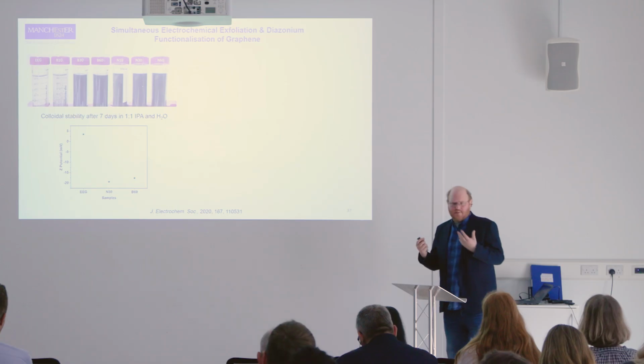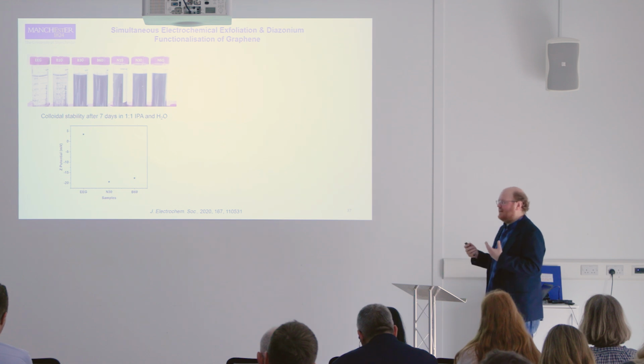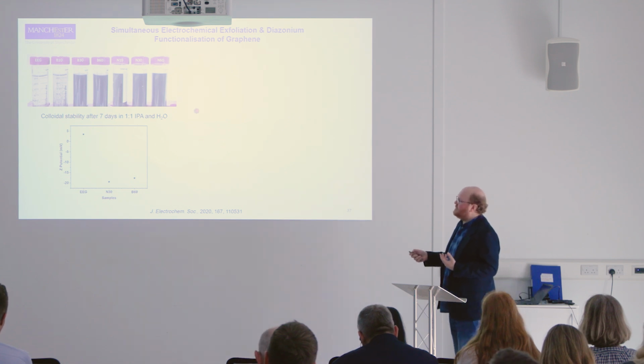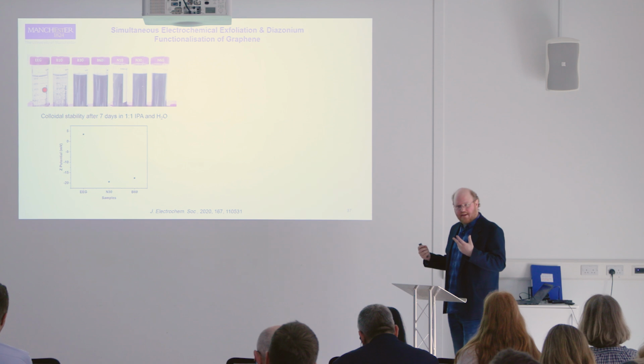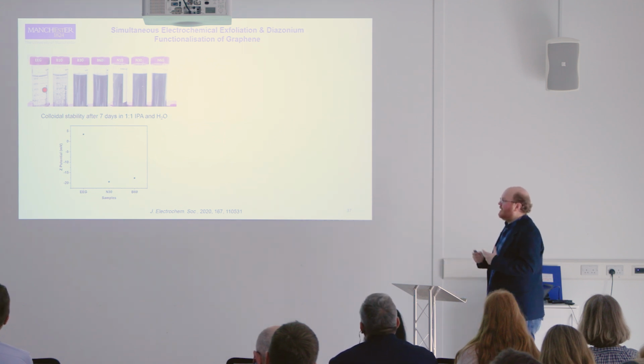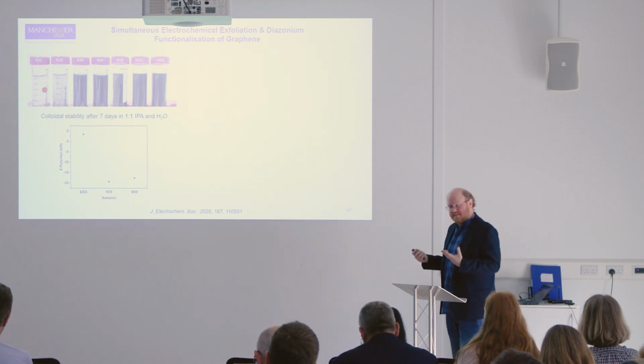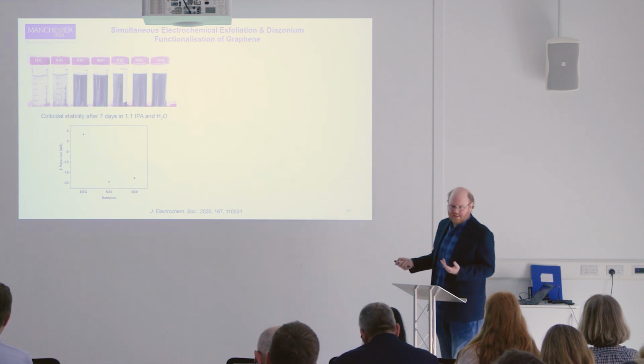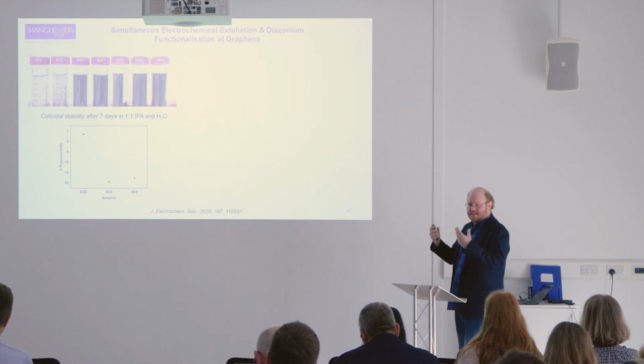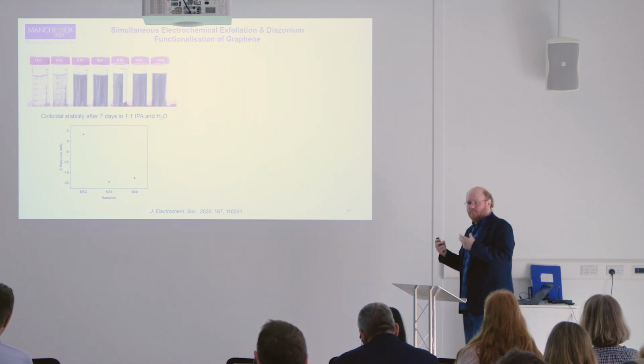And so one of the ways we can visualize this functionalization, as well as seeing the electrochemical performance, is that we get different colloidal stability. I said at the start, graphene is hydrophobic. It doesn't like being in water. It collapses out. If we exfoliate it in the presence of this diazonium, we can functionalize it and make it nicely water stable. This is in water and isopropyl alcohol. After 7 days, it's very nicely stable. It's not sedimented out. And that makes it more processable. We can use it as inks. We can use it in printing. We can use it in coating, things like this. And for the zeta potential as well, we see graphene is basically close to 0, but these ones have a much more negative zeta potential, which makes them much more stable in solution.